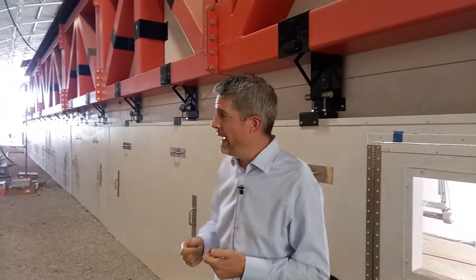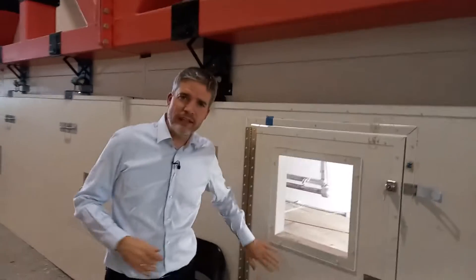To do that you need a heavy vehicle simulator — something that's going to generate those wheel loads. What they've got here is something called Titan, quite rightly so. This is the biggest heavy vehicle simulator in the world. It's 75 feet long — that's over 20 meters in terms of travel length. All the action happens inside here. The reason it's all contained is because the temperature of the asphalt is a big factor in the way it deforms, so we want to keep that controlled.